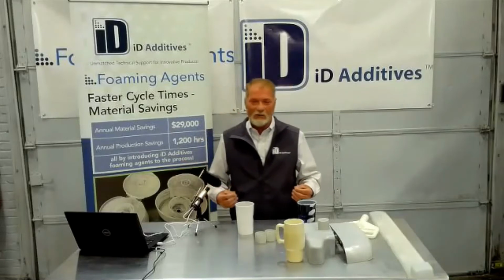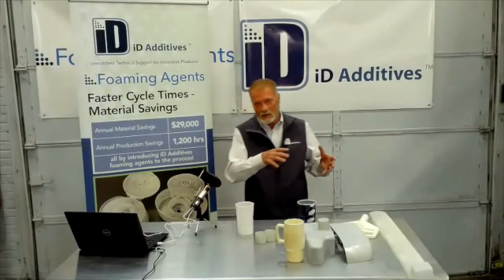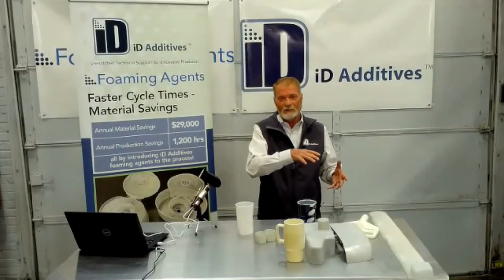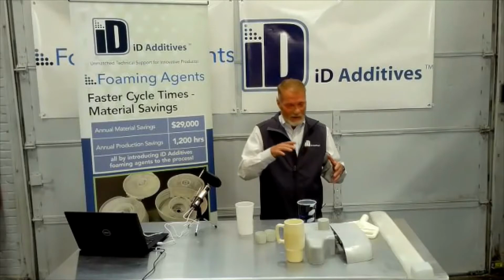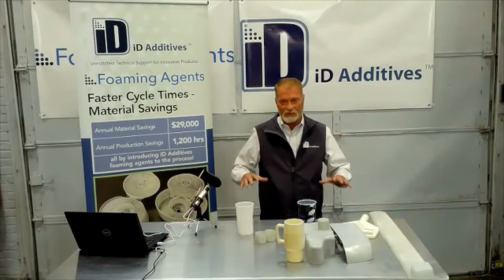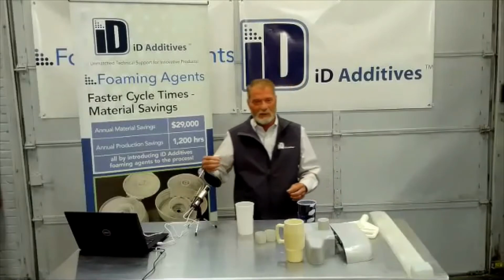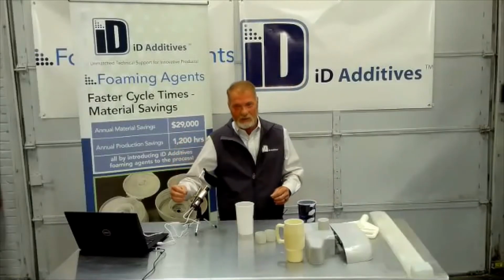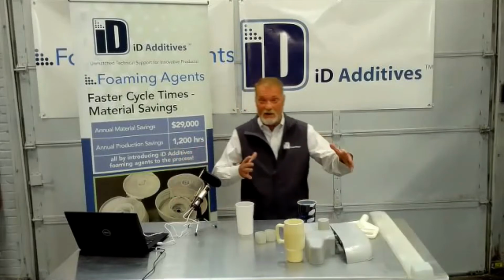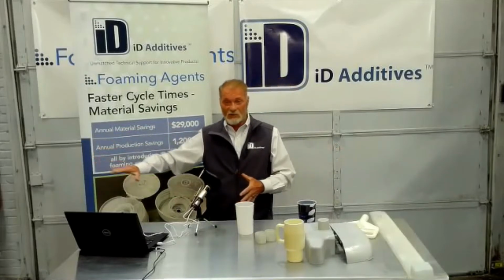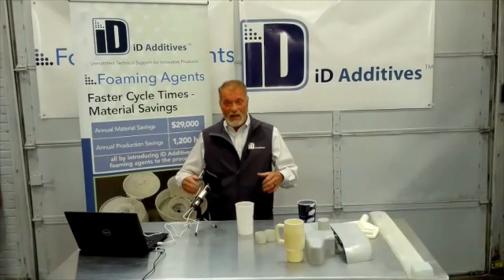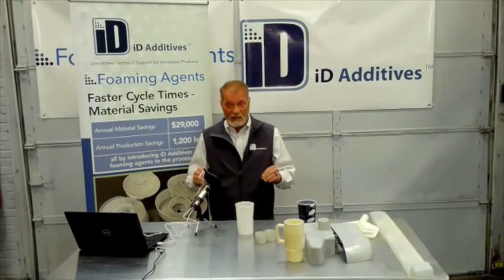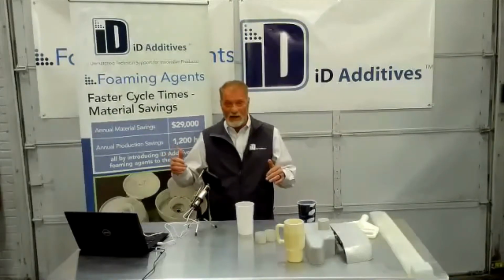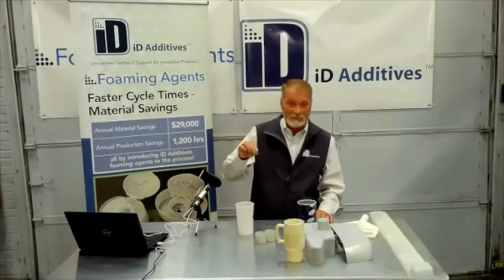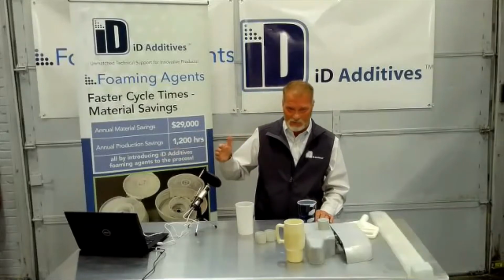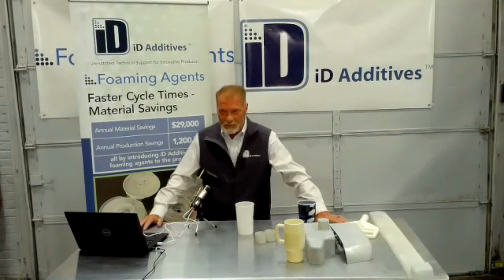And that's ideally where you want to be, because you want it to expand when it exits the barrel into the die. As soon as it exits the barrel, you're going to see a drop in pressure. It's going to start to go off. If you've got a melt pump, there's a drop in pressure. It's going to start to go off there. But I prefer it go off there than way back at the back of the barrel. So those pressures will allow you to add more foam and keep the part aesthetic. Whereas if you're pre-foaming a lot, you're going to get less weight and you've got to use less material because it's pre-foaming, it's getting out of control. So I hope that helps.